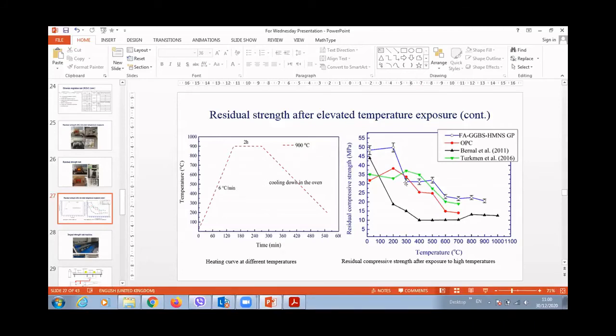For example, from 300 degrees to almost 500 degrees, we have a more stable product, and then it decreases. But the decrease is slow, not a sharp or quick drop.